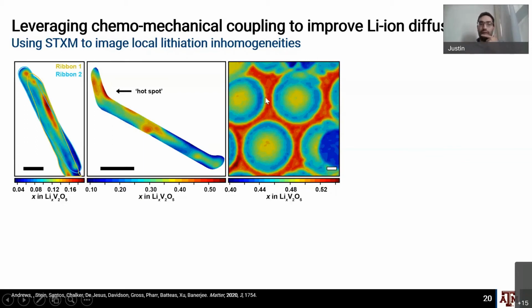And then also, if you look at the nanobowls as well, and this is not immediately obvious because the scales are blue to red, but if you actually look at the x in Li_xV2O5 at the bottom, you can see that the degree of inhomogeneity in the straight nanowire and the bent nanowire is actually much larger than in the nanobowls. And so this one ranges from about 0.4, which is firmly in the epsilon Li_xV2O5 regime, to about 0.6. Whereas these span, especially the bent nanowire, where this hotspot is extremely lithiated, a much wider extent of lithiation and exhibit much more inhomogeneity.